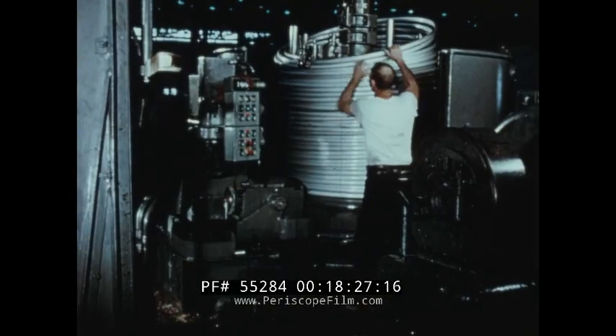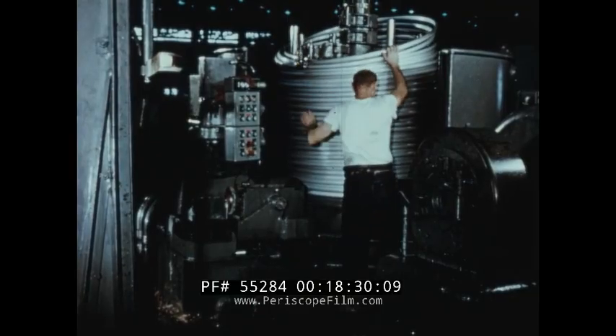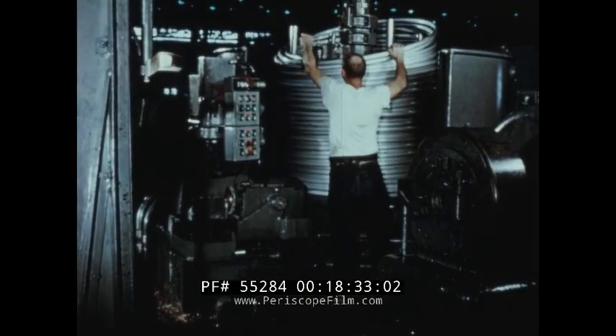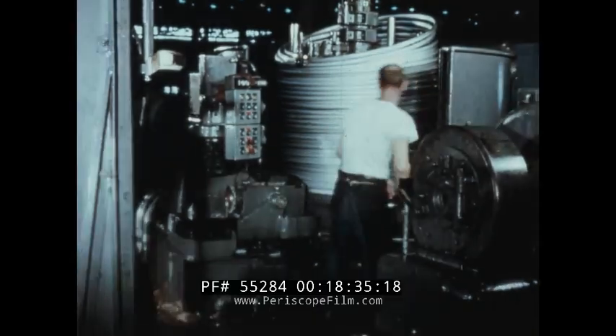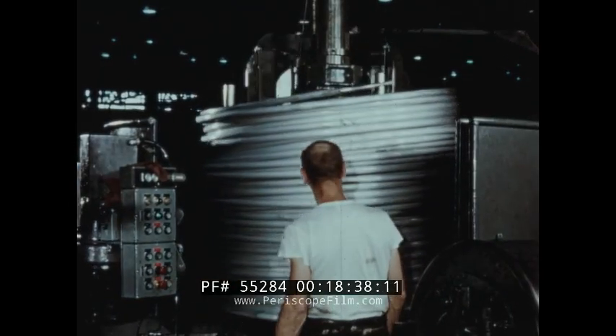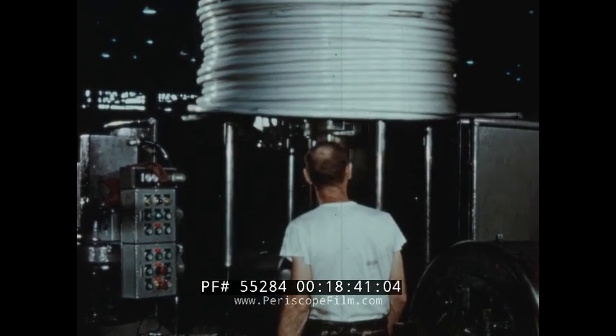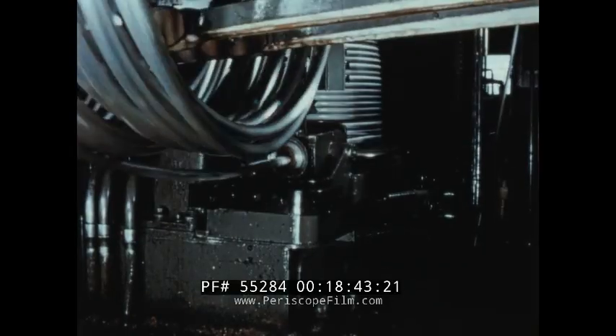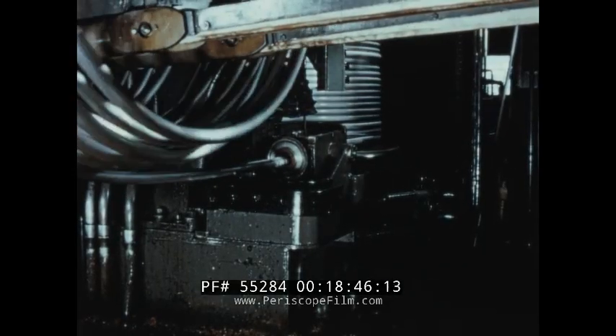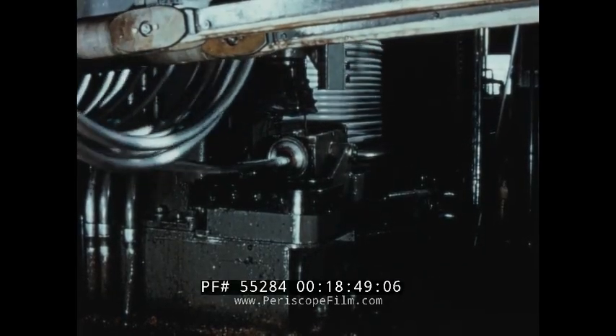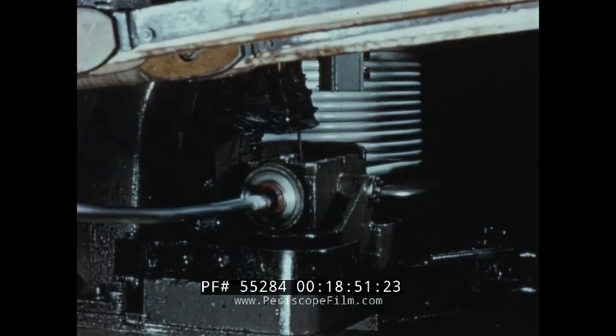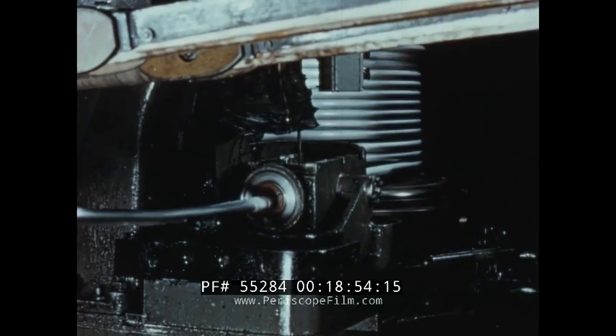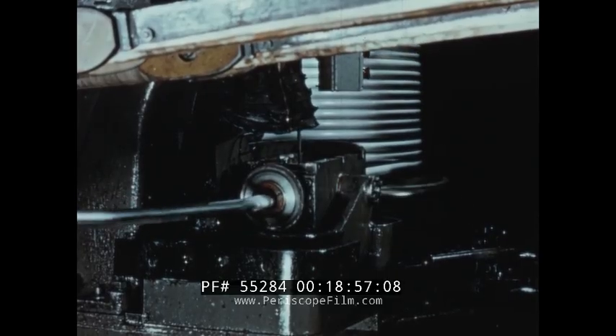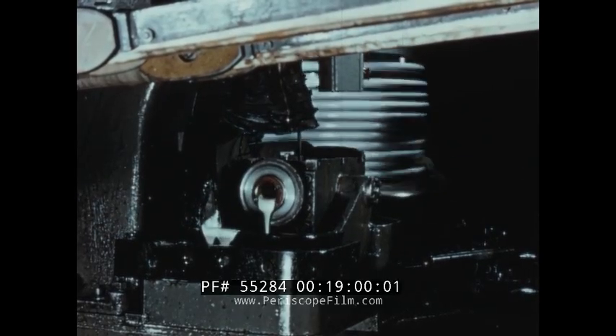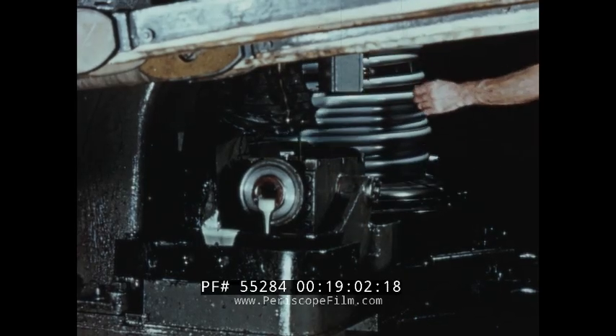Now, in the smaller sizes, tubing can be drawn in much longer lengths and much faster on a unit known as a draw block. This operates on the same principle as the draw bench. The tubing is pulled through a die, and a small floating mandrel is used inside the tubing to control the inside diameter. On this draw block at Lafayette, smaller sizes of tubing can be drawn and coiled at the rate of about 1,000 feet a minute. Our tube drawing operations are located at our New Kensington and Lafayette works.